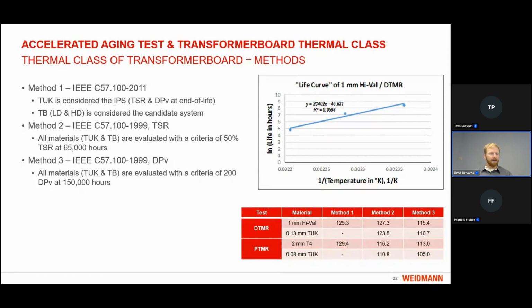The second method that we used was looking back at a previous version of C57.100, the 1999 version, where we looked at the tensile strength retention of the individual materials. So here we had all materials, both the TUK and the transformer board, being evaluated with an end-of-life criteria of 50% tensile retention at 65,000 hours. So different from the first method, where we were comparing the transformer board to the industry-proven system, looking back at 180,000 hours, in this case, we looked at all materials independent of each other at 65,000 hours. And then method 3, similar to method 2, looking back at the 99 version, but in this case, looking at degree of polymerization. Again, all materials are evaluated independently of one another, but with a criteria of a DP of 200 at 150,000 hours.